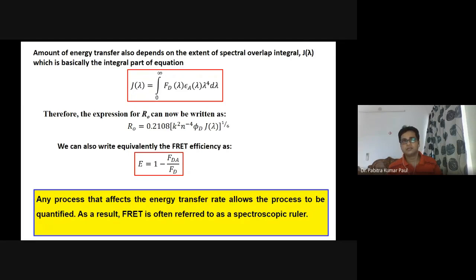This is the integral from 0 to infinity of FD, epsilon A, where epsilon is the extinction coefficient, and lambda to the power 4, lambda is the wavelength. So therefore, using these two equations, we can write the expression for R0, the Förster radius, in this way. And considering all these equations, we can also write the FRET efficiency as E is equal to 1 minus FDA by FD.